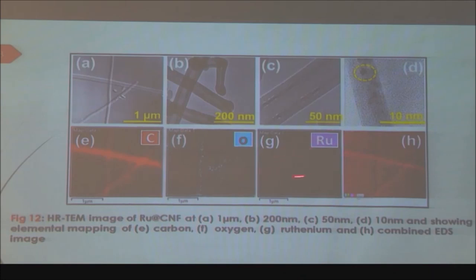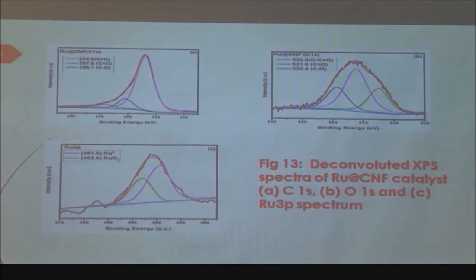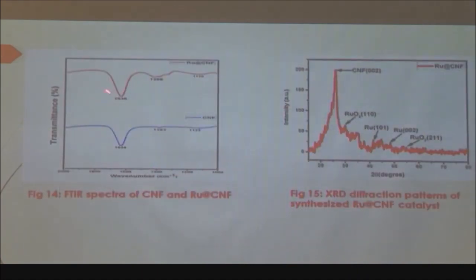So this is very little, maybe it is not visible here. As I told you, it is 2 to 3%, not a very high amount. So on this slide maybe you are not able to see those particles of ruthenium, purple color, but it is there on the surface. Again, we did XPS to confirm whether ruthenium is in the zero state or oxidized state. We found that both are present. Along with this, we also see different types of functional groups through the carbon as well as oxygen spectra. We did the IR spectrum and XRD. I'm not going into the details, but the main thing is that we made sure that ruthenium is present as ruthenium zero or oxidized RuO2 form.